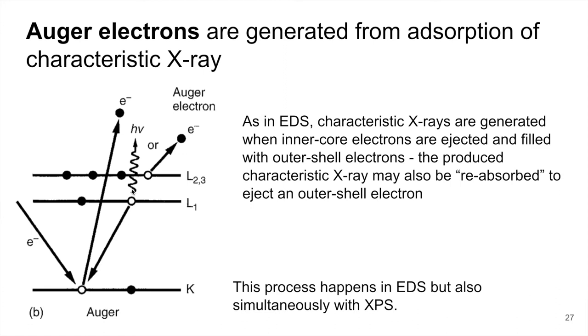So this is our characteristic X-ray that we used in EDS. But we're not done with that story yet though, because this characteristic X-ray can simply escape and be used for EDS, has a specific value tied to the difference between these two shells. But it can also, if it has a high enough energy, it can actually knock out another electron in an atom on kind of on its way out of the sample. So this X-ray can basically knock out another electron. So basically we have like a secondary effect. And that electron that's being knocked out is the Auger electron.